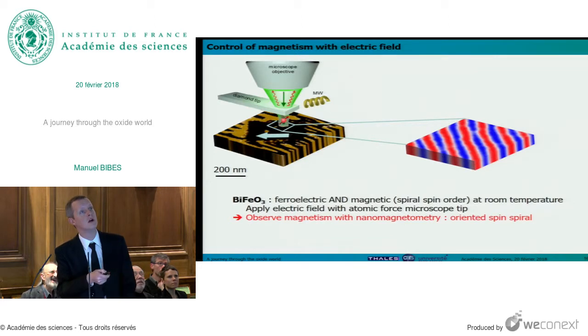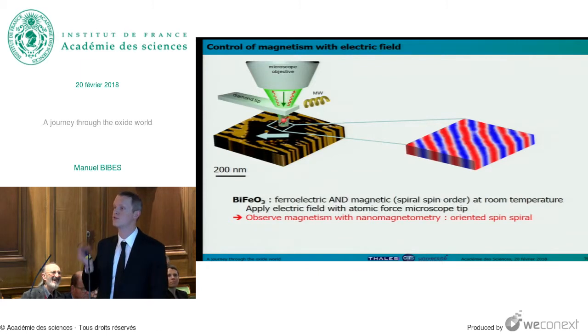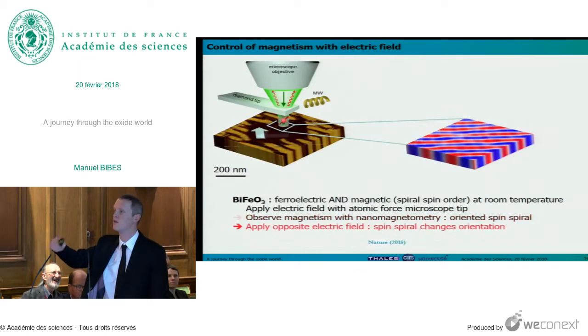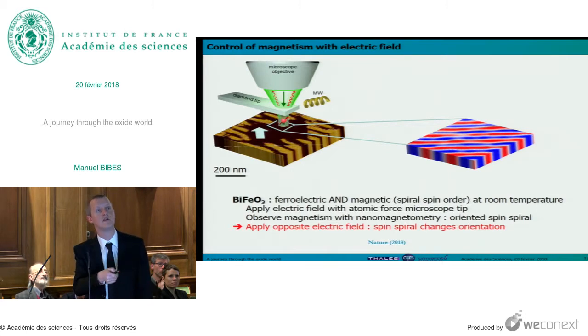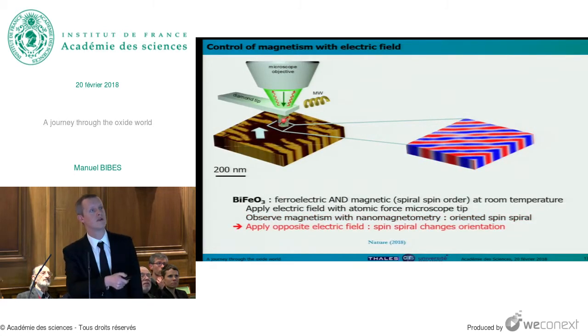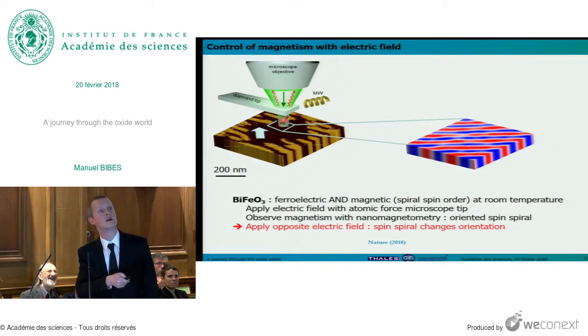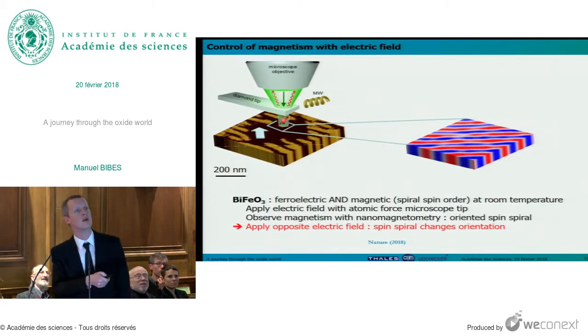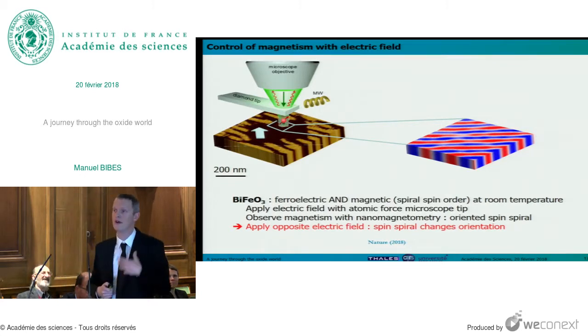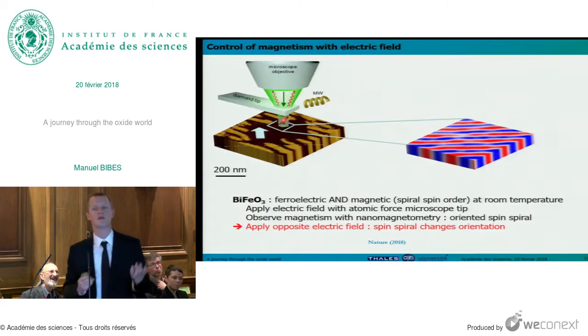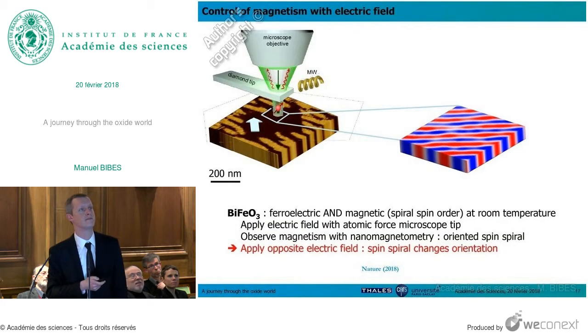And we are able to get this kind of picture that shows this nice red and blue stripe contrast, which is the indication of this cycloidal order that here has a well-defined orientation. And now if we come back to the sample and we apply an electric field in the opposite direction, we can reverse the polarization direction, and you can see that the direction of the stripe is changing by 90 degrees as well. So we are able to control the direction of this magnetic cycloid by an electric field. We control magnetism by electric field. This is much more convenient than to do it with a magnetic field.